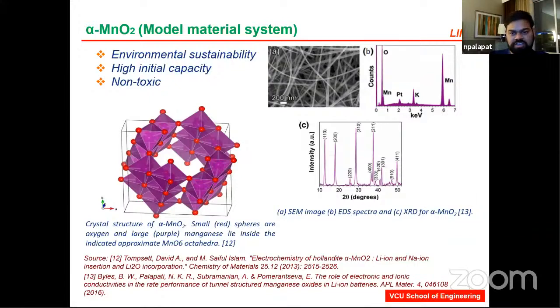I have some images of the characterization. This synthesis is performed by our collaborator. They developed these nanomaterial systems and they have given them to us. And I worked on depositing, then studying how these nanomaterial systems perform. The only drawback that we have seen is that though the crystal structure plays a huge role and brings huge benefit, we also notice that the structure itself can cause a very poor cyclability of this material system. So I'll talk further on this material system, why I'm saying the cyclability is poor, and what we can do to improve it.